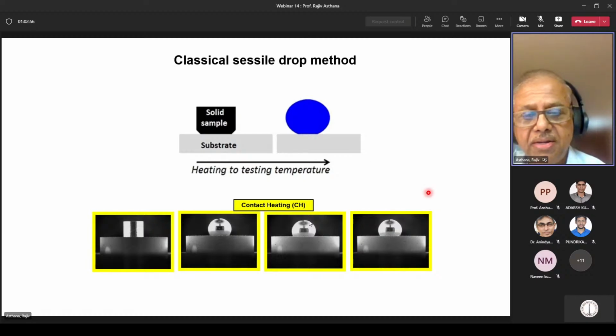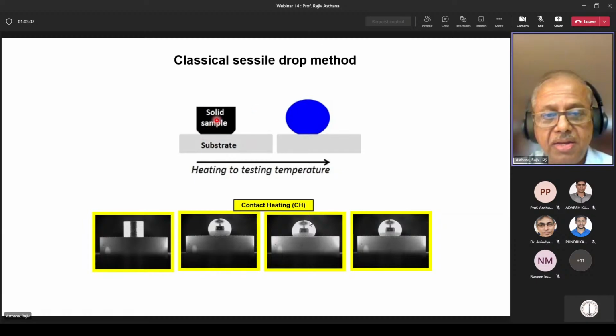So most wetting tests are done using what is called a sessile drop method and using a contact heating process. So the idea here is that inside the vacuum chamber where you have the furnace, you put the solid sample on a solid substrate and then heat them together until the liquid melts and begins to spread. And then you can image continuously the spreading process. And from that, you can determine the contact angle.